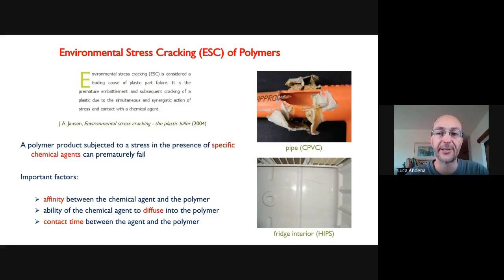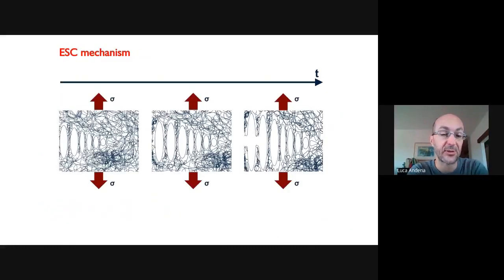So three critical aspects leading to ESC are a certain degree of affinity which is required between the chemical agent and a polymer, the ability of the chemical agent to diffuse within the polymer, and also enough time for it to cause an effect. And this kind of phenomenon can affect really a huge variety of products because most polymeric materials are susceptible to some kind of these environments. The generally accepted mechanism to explain ESC is related to the typical way we conceive failures in polymers.